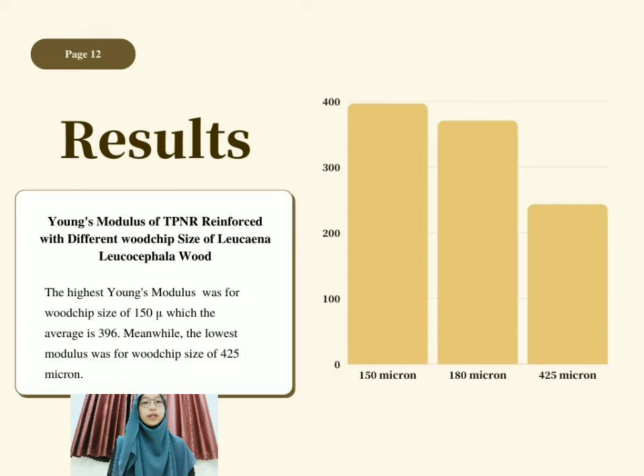Now, we will continue to our second result, which is for the Young's modulus of TPNR reinforced with different woodchip sizes of Leucaena leucocephala woodchips. In the graph, we will see that the highest Young's modulus was for the woodchip size of 150 micron, which the average is 396. Meanwhile, the lowest Young's modulus was for the woodchip size of 425 micron.